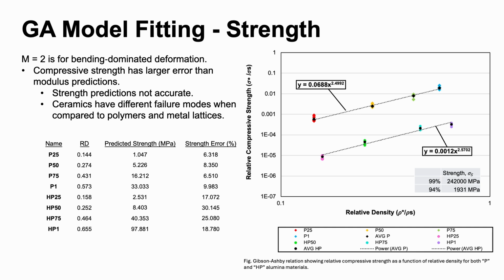However, we found a significantly large error for 94% alumina and a large error for 99% alumina when compared to the predicted modulus results. The exponent of 2 suggested that the lattice being compressed formed in a bending dominated way, which was incorrect.